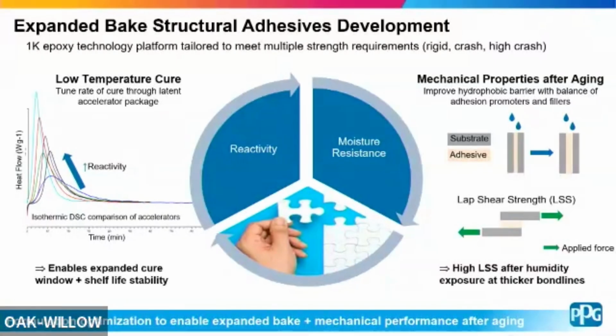So for the structural adhesives, this is going to be a 1K epoxy platform, really tailored to meet different strength requirements depending on where it's being applied within your vehicle. So a rigid, a crash, or a high crash adhesive, all of those are commercially available. And there were a couple key technical innovations that were required, key focus areas for our team to enable this platform. The first being the reactivity and then the moisture resistance. So on the reactivity side, that's really targeting that low temperature cure. So you need to have a more reactive system in order to get cure at 140 C, 10-minute bake times, if that's your minimum cure target.